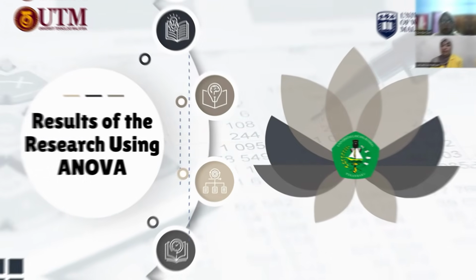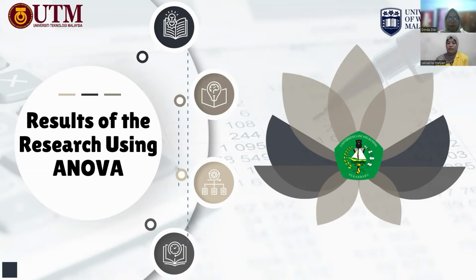Thank you, Salsabila. Good afternoon, everyone. Now, let me present our results of the research using ANOVA. Let's look at our ANOVA statistical analysis. We tested whether temperature variation significantly affects the Marshall characteristic. We analyzed 7 parameters at 4 temperatures: 130 degrees Celsius, 135 degrees Celsius, 140 degrees Celsius, and 145 degrees Celsius.